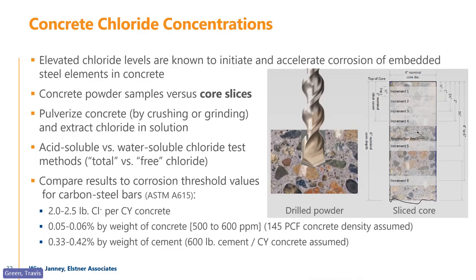These numbers are generally used to talk about corrosion thresholds, right? And there's a bunch of different thresholds depending on the bar type. There are also different ways that they're presented, right? So I've given you 3 basically for black bar here. VDOT uses pounds of chloride per cubic yard of concrete. You'll also see percent by weight of concrete, and you'll also see percent by weight of cement. Just be careful when you see these numbers. They do actually matter. You can go back and forth between them pretty easily, but they can be confusing, at least for me.